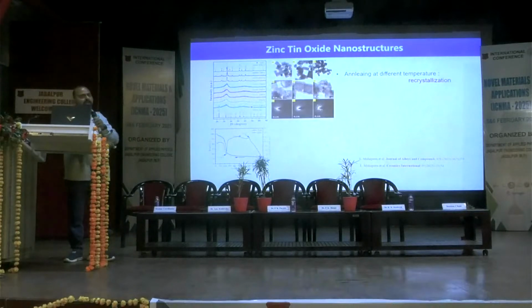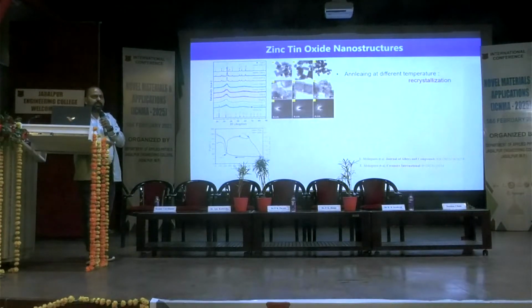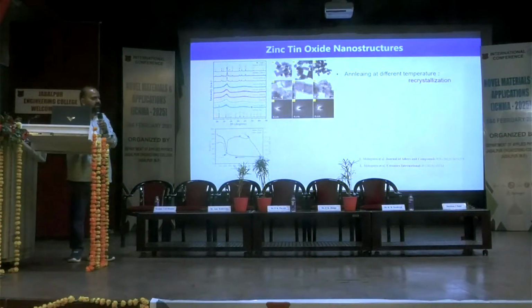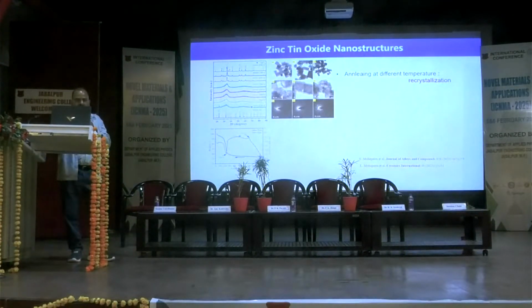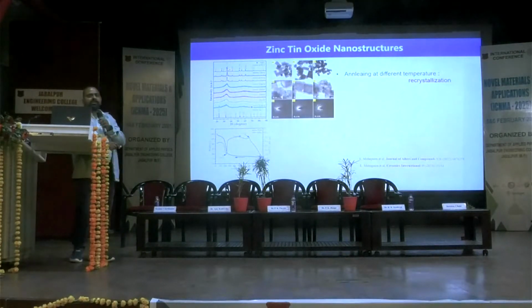So earlier we developed some kind of nanorods directly on the substrate, but it seemed difficult at the very beginning to grow the structure. So we started with preparing nanoparticles, and we developed nanocubes of zinc tin oxide. And then what was our first impression? Let's look at the surface profile.